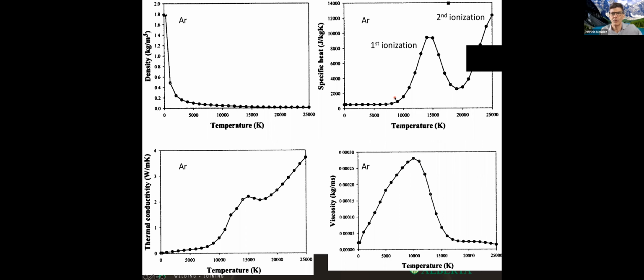What are those squiggles? Those squiggles are related with the ionization. So same horizontal axis on the graph on the top right, very large temperatures. And what do we see? This is specific heat on the vertical axis. This curve looks very much like a heating curve in a metal. So we have a specific heat at relatively low temperatures. When we have a phase transformation, the specific heat is high because we have some amount of latent heat involved.